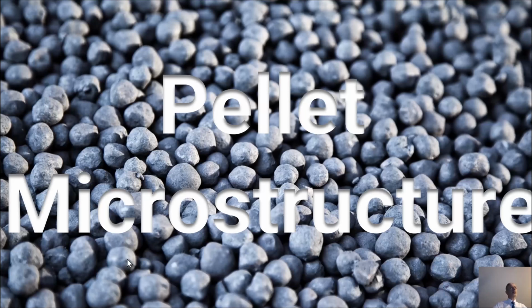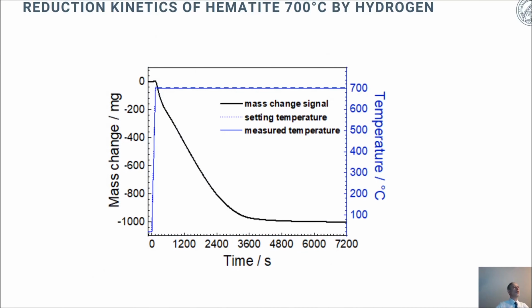And we now take a little journey through the microstructure of these pellets, which are pelletized products of the original iron ores. And we start with hematite, so Fe2O3 as a starting product. And we conduct this reduction analysis at 700 degrees centigrade, and we use pure hydrogen for this. This diagram shows the mass change as a function of time.